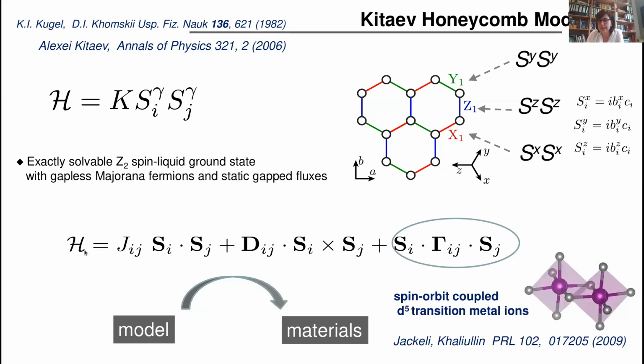So in a spin system, you expect to have a Heisenberg interaction, a possible Dzyaloshinskii-Moriya interaction if the spin orbit coupling is non-zero and you have no center symmetry, as well as the symmetric term, also called pseudo-dipolar interaction. This is also proportional to the spin orbit coupling.